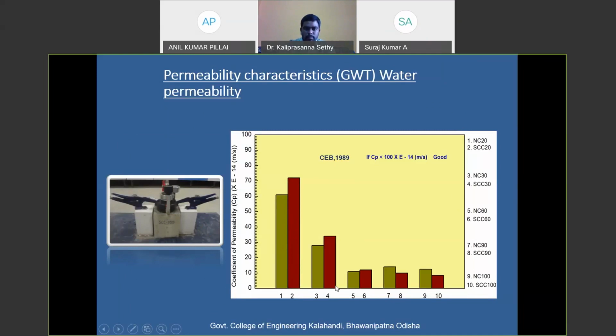This is the bar chart for M20, M30, M60, M90, and M100. So it is showing that the low strength concrete has a higher permeability value than the high strength concrete. Though it is showing a higher value, still as per the standard given by the Concrete Society, if the coefficient of permeability is less than 100 to the power minus 14 meter per second, the concrete is categorized as good concrete. And you can see the maximum permeability value we got is around 75. So you can say all the concretes which we have developed are showing a very good result for permeability using this German water permeability test.